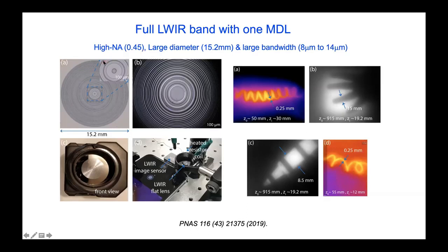In this case, the lenses were made on silicon, because silicon is transparent, and there's a relatively thin polymer, something like 10, 12 microns thick on top, which was patterned. And I'll show you shortly that that's not a limitation. You can go straight into silicon as well. So you can see what they look like, and they're coupled with, in this case, a Seek Thermal infrared camera, and we also used it with a FLIR infrared camera. You can see images which are reasonably good.